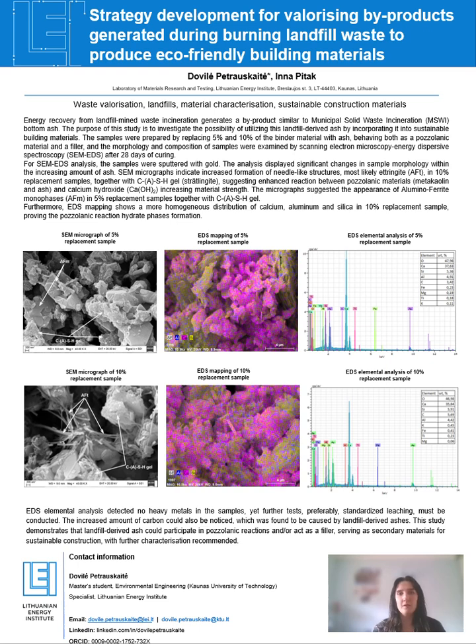Of course, some unreacted particles are still visible, suggesting that the reaction is still partial at this stage. And this morphology implies that the ash participates in hydration, but not completely. It contributes both as a reactive component and as a filler.